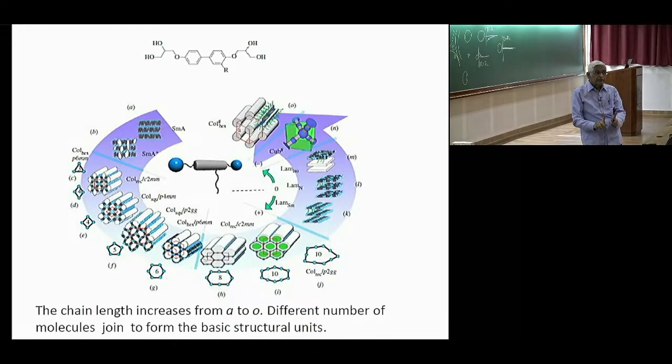So these are actually standing up like that. Your rod-like molecules fit into that, and in any case, all of them have aliphatic end groups, so they also fit in properly. So you get the orthogonal alignment.